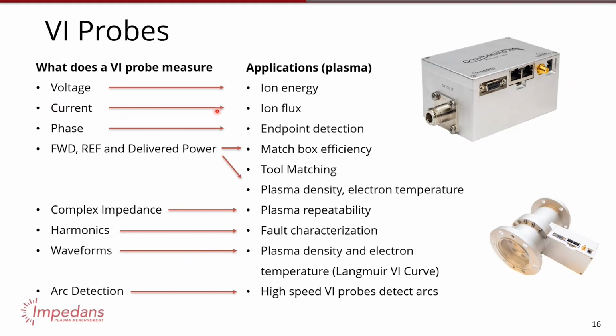With the current, you can get the ion flux, or in other words, etch rate and dep rate. With the phase, you can do things like endpoint detection, although all of these contribute to endpoint detection. For forward, reflected and delivered power, you can look at matchbox efficiency, you can do tool matching, and if you use some simple models, you can actually get plasma density and electron temperature, provided that you're taking measurements outside of the 50 ohm region. I'll go into detail soon on what the 50 ohm region and non-50 ohm region is for those of you not familiar.